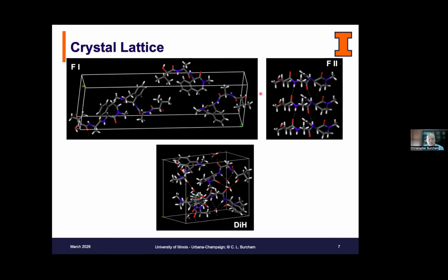This difference between the conformation of the molecule within the lattice and relative to one another within the lattice led us to postulate that the interconversion kinetics between Form 2 and Form 1 would be extremely slow. And as long as those interconversion kinetics were essentially non-existent over the intended shelf life of the product, then we knew we would have a kinetically stable polymorph that we could carry forward.